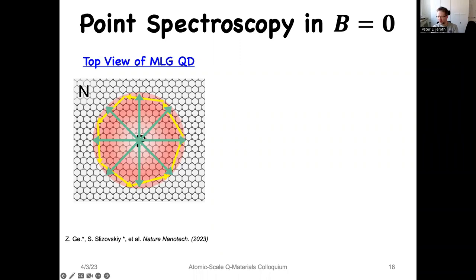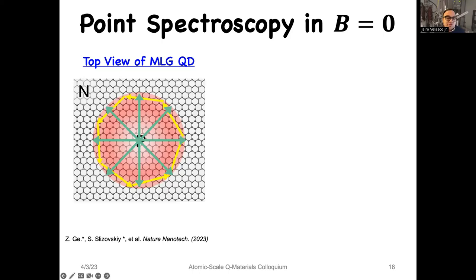Q&A: Do you anneal the sample in UHV after nano-grooming, and do contaminants migrate back? The sequence we use for high yield and clean surfaces is: first an argon-hydrogen anneal, then AFM tip cleaning, and then we bring the sample into UHV for the UHV anneal. By following this sequence we are more likely to have large clean areas on our graphene films. Omitting any step reduces reproducibility.